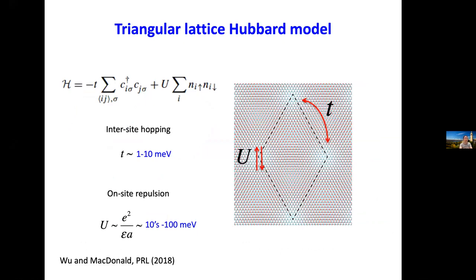a realization of the single band Hubbard model on a triangular lattice with 2 parameters. The on-site Coulomb repulsion is calculated to be on the order of tens to hundreds of milli-eV, and the intersite hopping parameter T is somewhere between 1 and 10 milli-eV. The hopping parameter decreases exponentially with decreasing twist angle, so this gives you a knob to tune the U/T ratio.